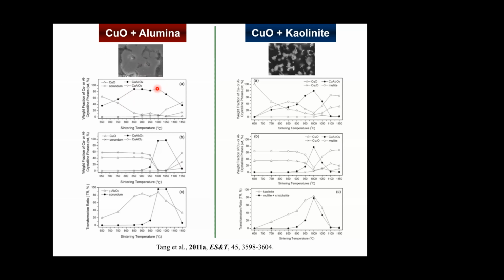this experiment with copper oxide and alumina, we find it's actually a very interesting window that you have to shoot, both for gamma alumina and for alpha alumina. And the window is around 1,000 degrees Celsius. A lot of people consider that when we want to stabilize the waste or make it less leachable in the geoenvironment, we burn at as high a temperature as possible, because we can stabilize much better with a much stronger thermal effect. Actually, it's wrong. If you really look at this example, we're telling you there is a window to shoot. That's probably between, I would say, 900 or at most 1100. That is the window you have to shoot.